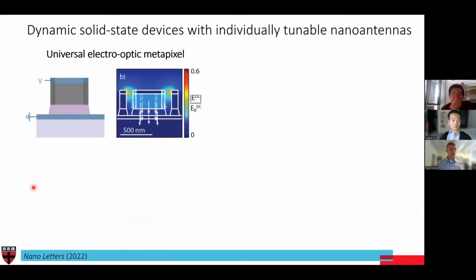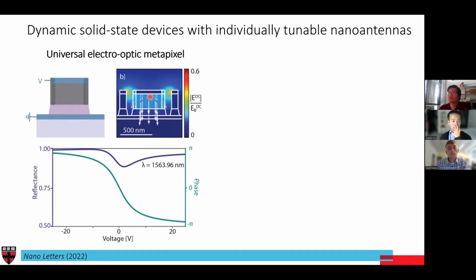And we actually also went a step further. After I graduated, a couple of students in my old group moved on to design structures where we take an individual nano antenna and we apply a voltage going through the material. Here in gray is silicon, and then underneath is lithium niobate. And what this allows us to do is individually control the response of each of these nanostructures. And by applying voltage, we have nearly 2 pi phase control,